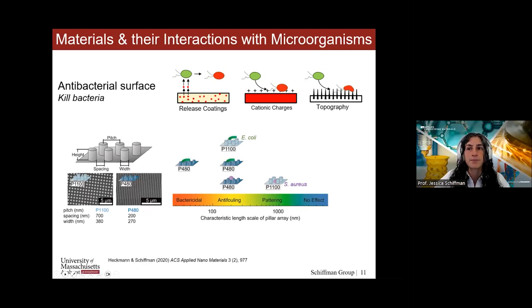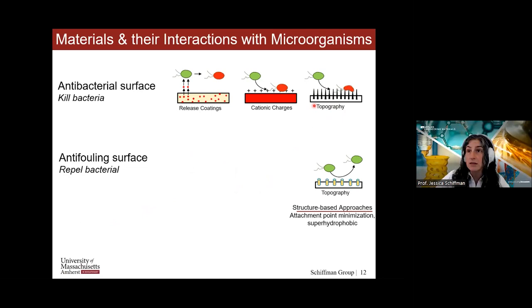And so with this, I've introduced that while topography can kill bacteria, it also can be in our second category, which I'm going to call an anti-fouling surface, or one that repels the bacteria. The mechanism by which we think this works is that it decreases the amount of attachment points that the bacteria might have. And so these topographies are also often hydrophobic. Another example of this kind of topography is the lotus leaf, which many researchers have replicated to show that we can make these repellent hydrophobic surfaces that mimic nature. Okay, but let's take a step back.